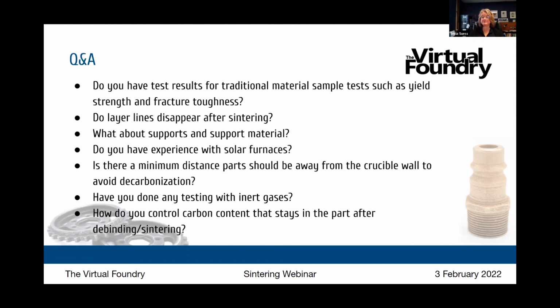So we use that refractory ballast material to provide support during debind and sintering. And this is an interesting side effect of the material. So metal is an excellent conductor of heat and plastic is not. And one of the key limitations of printing an overhang with a 3D printer is cooling the plastic. So what we've found is that you can get extreme overhangs with this material, more so than you could with plastic. So in this example, I'd always said I would never do a benchy, but I wound up doing a benchy. So this is the copper benchy, but this is printed completely without supports, including the bridge inside of the cabin and the bow. So supports are less important with this material. You can get greater overhangs than you could with plastic.